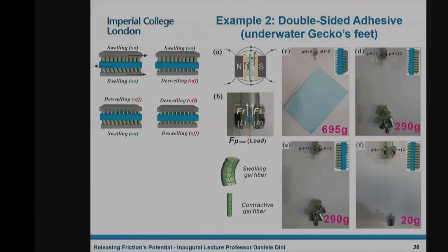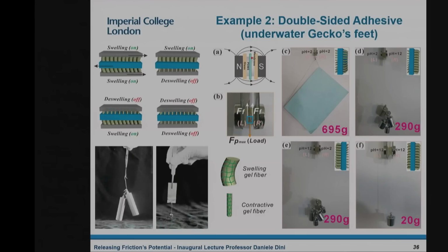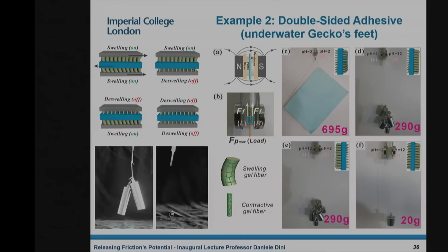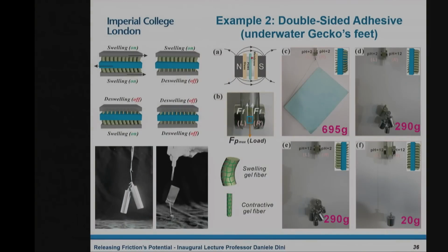Now, simply by changing the pH on one side of the membrane or the other, you can lower the friction. So if you are in a situation where you've got low pH on both sides, you can hang any weight you want on this system when it's squashed between and hold quite a lot of load. But then if you go and increase the pH dramatically, you get a very slippery system. So your adhesion forces, your weight carrying capacity, goes down drastically. And in fact, there's an experiment showing here that with the same kind of tweezers, if you put the same type of apparatus, you change the pH of the solution with which you wet the system, you get completely different holding capacity in the system. And that, I think, is a nice way to show nice engineering through friction.